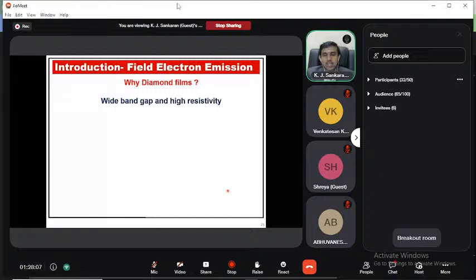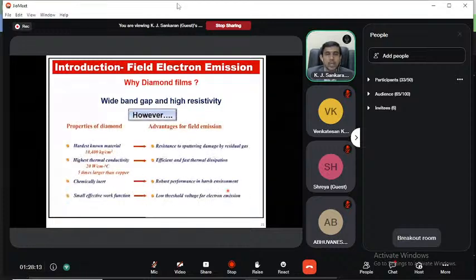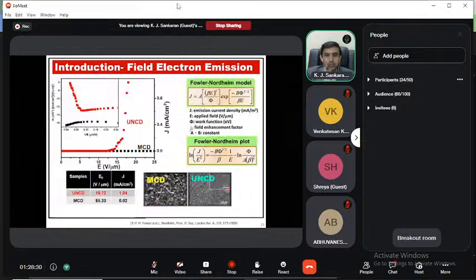Then there comes the diamond film. But as I mentioned before, diamond film is a wide band gap and high resistivity material. Then how can we apply this material for electron emission? There are some specific properties of diamond which really make it a very good field electron emitter. Those are that it is chemically inert and has a small effective work function, which can lead to robust performance with low threshold voltage. So we have compared the electron emission properties of UNCD and microcrystalline diamond.